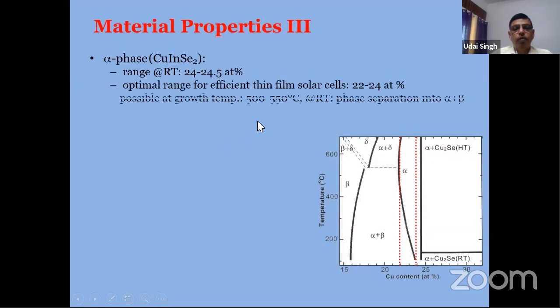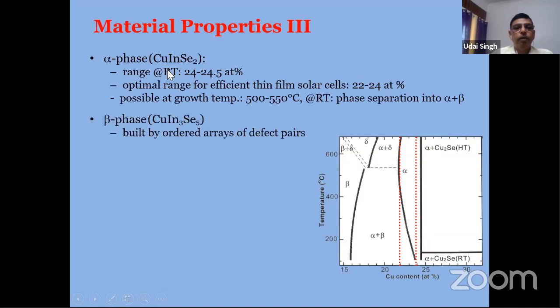The only problem is to have a pure phase. If you see the phase diagram, if you want a pure alpha phase, the alpha copper indium selenide, and you go beyond this, copper is more than 25%. You have this copper indium selenide phase plus copper selenide, which is very highly conducting. So you will get a shorted device. You will not get any solar cell.